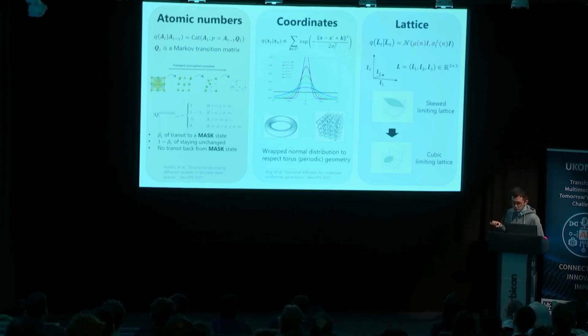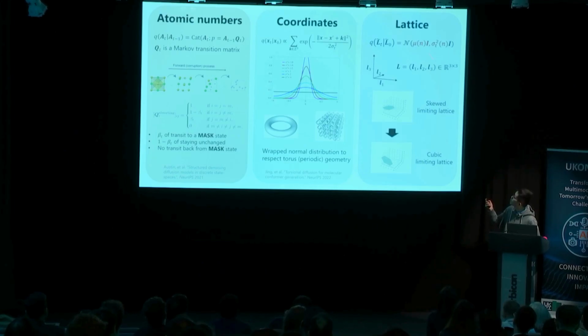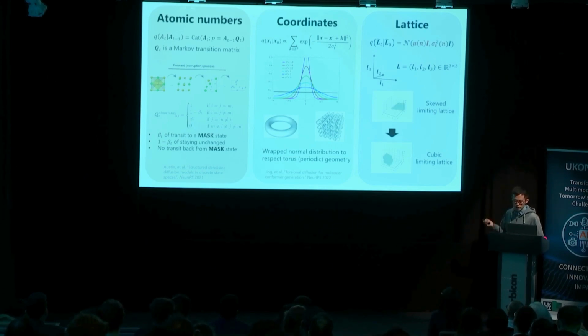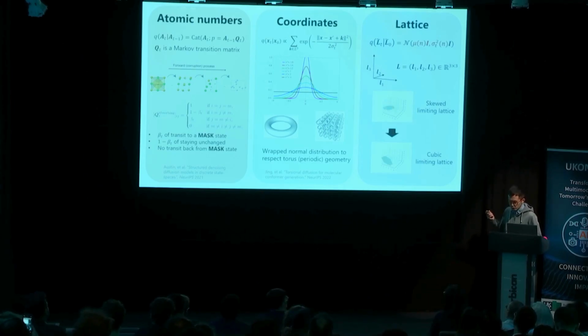Finally, it's about the lattice. The lattice is basically the periodic box that I mentioned earlier. We just use the standard VPSDE, but we slightly adjusted the limiting mean and the variance of this distribution, because we found that if you don't make any changes, at the limiting distribution you have a very skewed box, which introduces a lot of instability during training. By modifying this, you can have the limiting distribution be a cubic box, which is much more stable during training. Combining all these innovations, we built a diffusion model specific for materials, which I will show later is quite useful for the model performance.